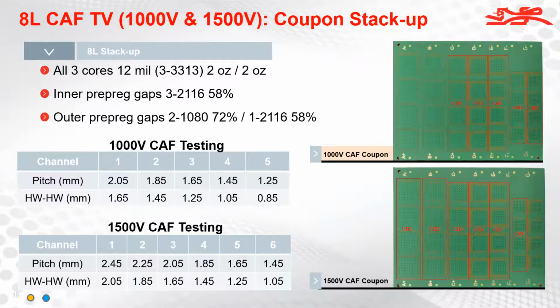How much dielectric do I need between my two conductive layers to be able to ensure that this is going to have a long life in the field on a car? I mean, you're looking at a design target of 20 years of operational functionality. And if you have CAF failures when you put these high voltage systems in every year or so, you're going to be spending a lot of money swapping out boards in cars. And so you need to have a material that's tested at much higher voltages to be able to tell the user of this material, the OEM, that in an accelerated life test, we can see that this material will last X number of years. And without that information, it's really difficult to predict the capability of the material.